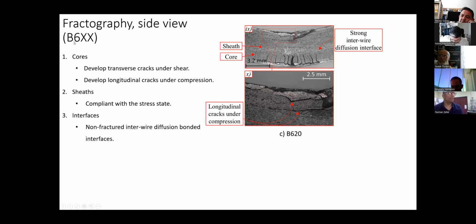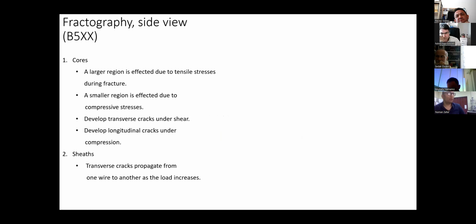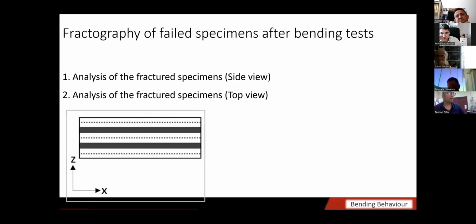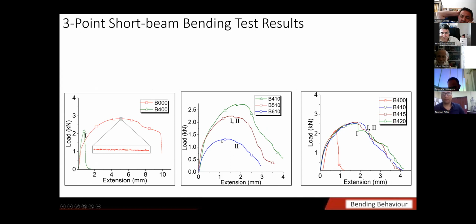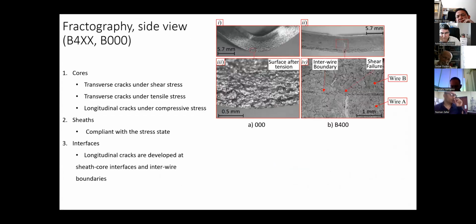So can we say that for the wires which have a core diameter of 6 millimeter, the cracks at the interwire boundaries are not formed because it has a strong interwire diffusion interface? We can say that, but the fact that no cracks are seen at the interwire boundaries does not have anything to do with the strength of the bulk material. It has something to do with the preference of the formed cracks in the material. Because if it was the case that larger core diameter results in stronger interfaces, then we would not have seen anything like this. This is the same material which has the lowest failure load. It has something to do with the preferences of the cracks.